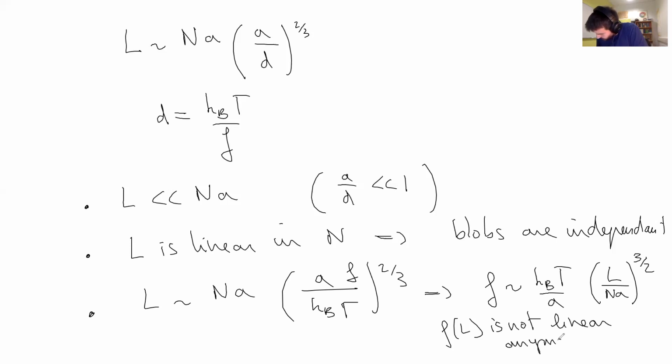That is normal, it is a limit where we are really putting a lot on the system. And there is an exponent 3/2 that is reminiscent of the Hertz exponent. If you indent with a sphere an elastic material, well, the force indentation law will be typically 3/2 as well. So we often call this quantity a Hertz-like force indentation law or force elongation law. All right?